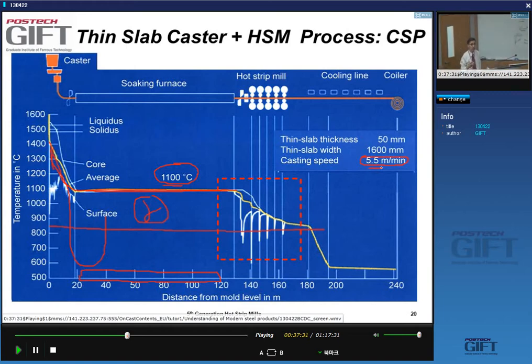Now, if you compare this with the exit speed of a hot strip mill, it's very, very slow. Obviously it's higher than this. What I want to say is if you were to feed this strand straight into the finishing mill, it would run very slowly. Obviously you don't want this. You want to have high speed, and that's the trouble. You cannot cast faster. So you need to have more casters in parallel. And of course, they will produce strip, or bars rather, and so you need to keep them ready so that they can be rolled one after the other. Okay?